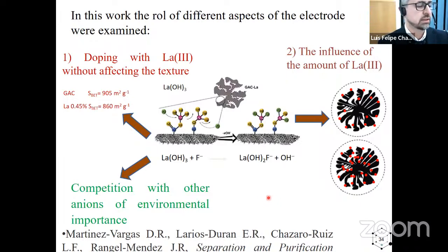The first one was to study the influence of a minimum amount of lanthanum to promote a better dispersion of this element or lanthanum clusters, and thus to avoid the occlusion of the micropores of this material. Also to study the influence of the amount of lanthanum and the changes of the textural properties, as you can see in these 2 figures. And also we studied the competition with other anions of environmental importance, but I'm not going to talk about this. I think I don't have enough time for this. So only these two aspects.